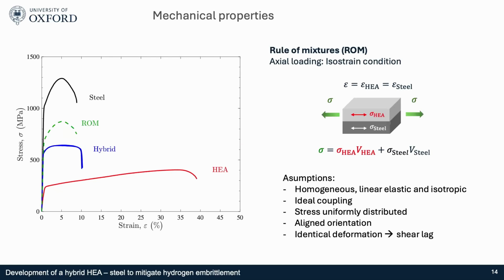And then we did some theoretical approach following the rule of mixtures to see how far our results were from the theory. And we obtained this green curve with the rule of mixtures. Knowing that the rule of mixtures has several assumptions, like an ideal coupling between the two materials, uniformly distributed stress, and aligned orientations, our samples are a little bit below because maybe the interface is not totally straight and maybe there are some little cracks that we don't see, but it's similar.